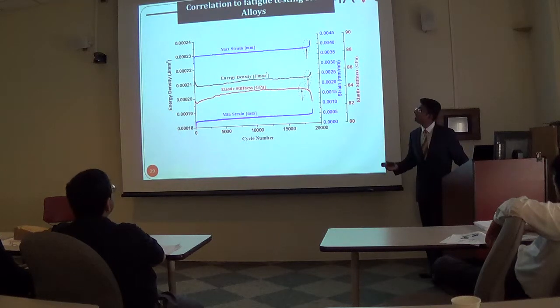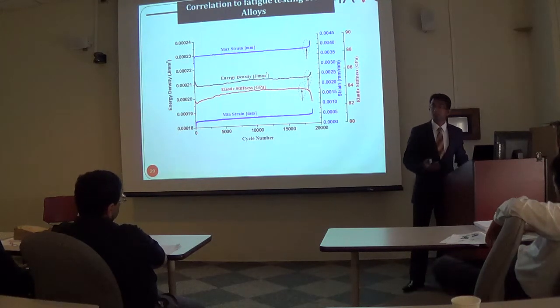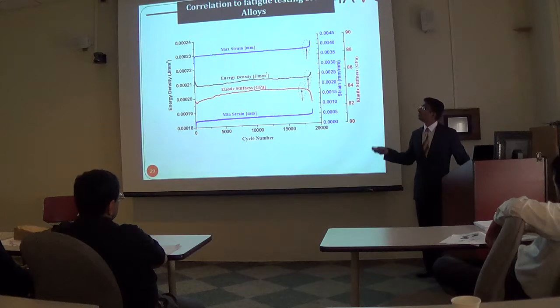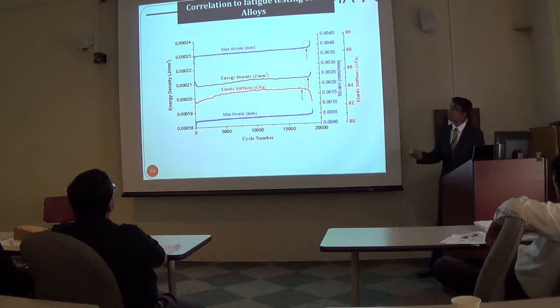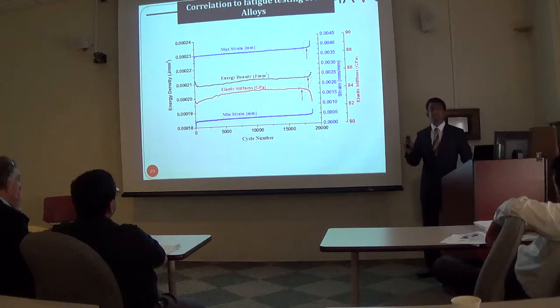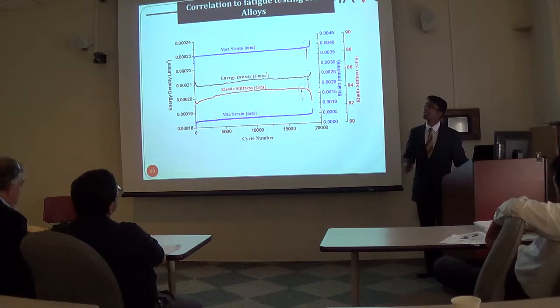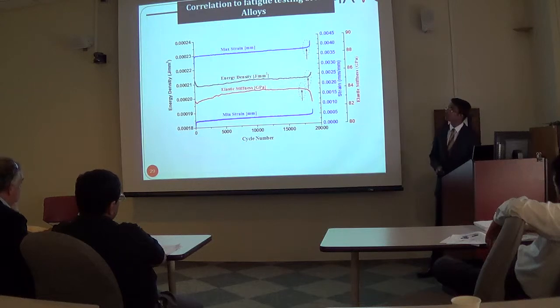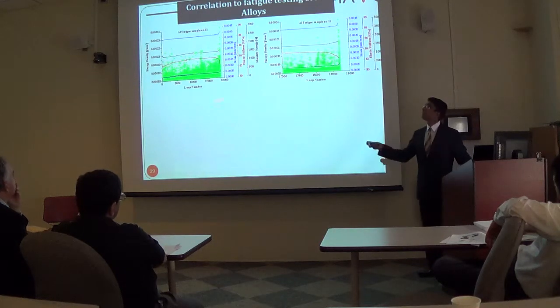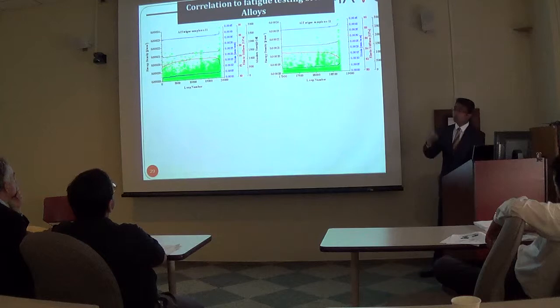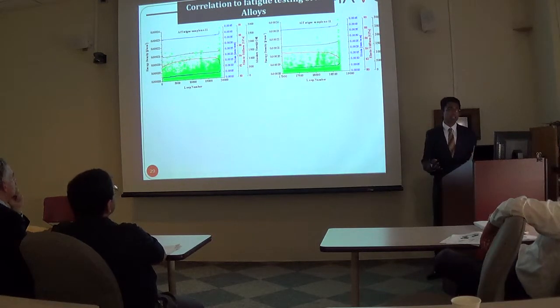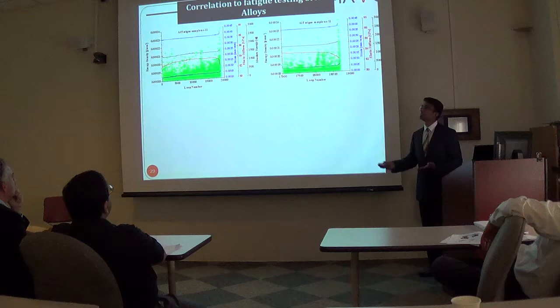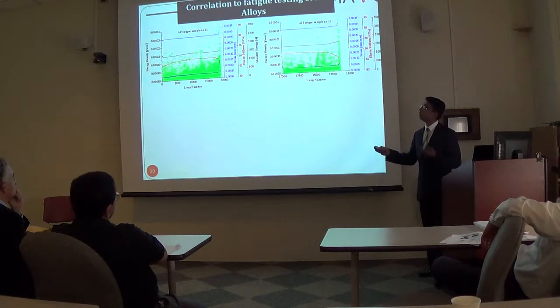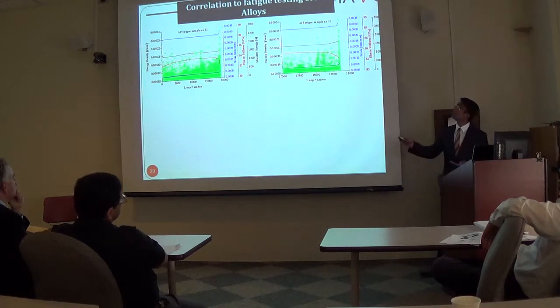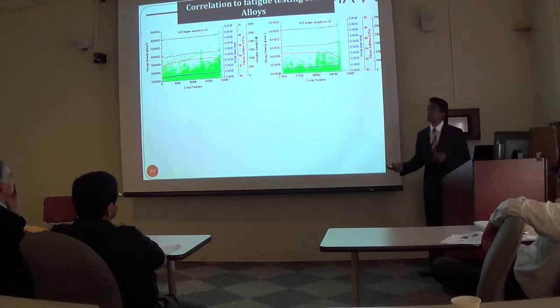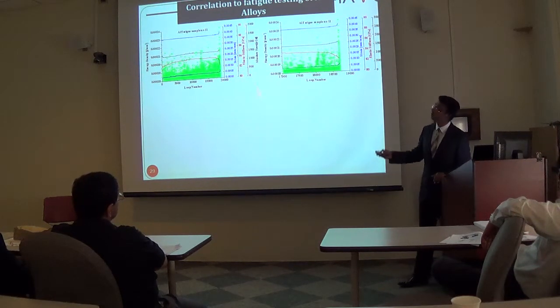Now, to see if the AE features can be reliable in detecting damage during fatigue testing of these materials, several fatigue parameters such as energy density, the stiffness, and the strain that were extracted independently from the DIC were correlated with the extracted AE features. And as you can see here clearly, usually AE testing during fatigue produces a large set of AE data. And so it's quite complex to understand exactly what each source corresponds to. So the full field DIC parameters that are extracted are then utilized to interpret the AE features that are collected in real time.